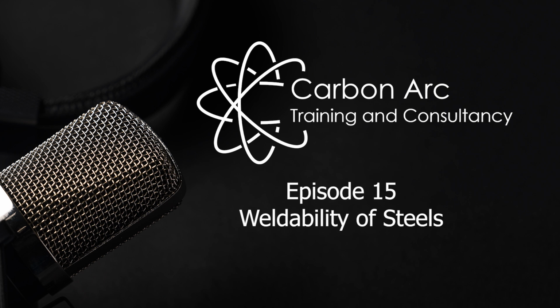The first one: hydrogen-induced cold cracking. That sounds particularly nasty. I've heard it called cold cracking, right, because it happens after cooling, and HAZ cracking, because it's usually in the heat-affected zone. Yeah, those are common names. But the one that always gets me is delayed cracking, the idea it can just appear hours, maybe days later, up to 72 hours, you said. That's like a ticking time bomb in the metal. It really is insidious, that delay. And while yes, most hydrogen cracks pop up in the heat-affected zone, the HAZ, it's worth knowing they can also form right in the weld metal itself.